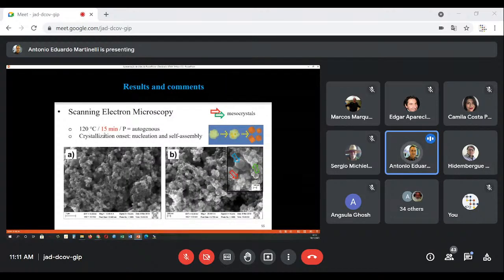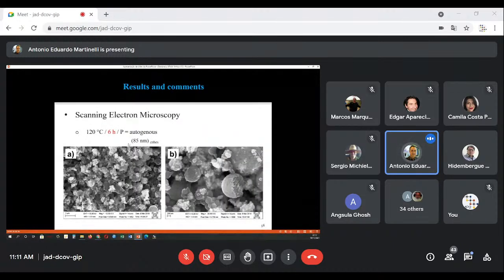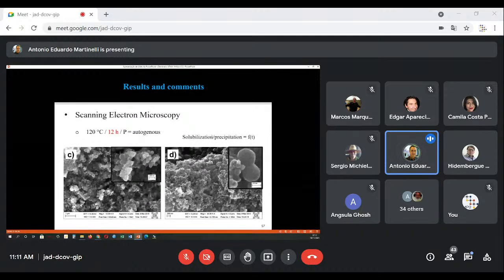120 degrees C, 15 minutes, autogenous pressure. Then we see the onset of crystallization from the amorphous phase in solution and self-assembly of the first mesocrystals, as shown here in this arrow. So here we have the amorphous phase, and here we have the first mesocrystals. Increasing the time from 15 minutes to 6 hours, we didn't change the pressure. Now we start to see some nanoparticles of cubic geometry still dispersed in an amorphous phase, of average size 85 nanometers. Increasing to 12 hours, we see